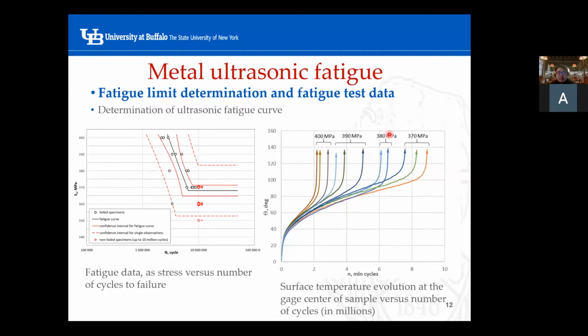And finally, this rapid temperature growth part at the final stage is what we call phase 3. At this phase, we have a very rapid temperature increase due to the initiation of micro cracks. So that's the 3 different phases of the temperature profile during ultrasonic vibration fatigue.